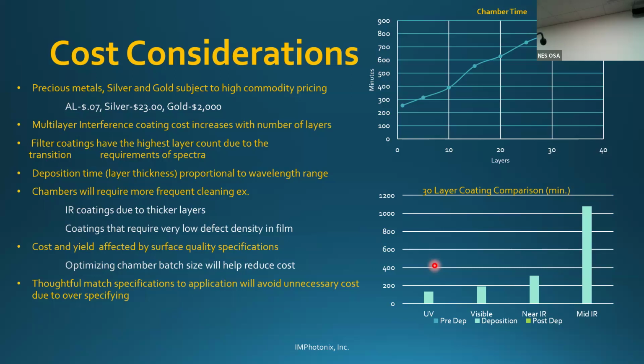Also the wavelength you're working with affects the deposition time, since interference coatings are a function of the thickness, and the thickness is a function of the wavelength. The further out you go into the infrared, the thicker the layers are going to be. The thicker the layers are, the longer the deposition time, the more expensive the coating. So these graphs just illustrate those relationships. The important thing to remember is that when designing a coating, you want to work with the coating vendor to optimize the coating for the application, not to over specify it.